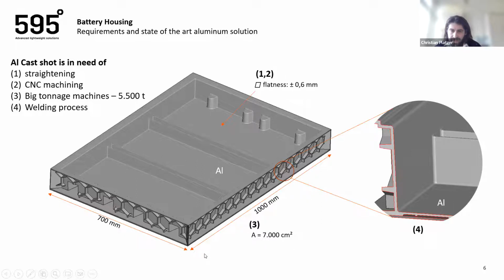And by considering this rather small dimension of a battery system, you already need a 5,500 ton machine in aluminum die casting to be able to cast it. And although there is this hype of die casting machines getting bigger and bigger, we somehow learned that there's not so many on the market, and it's very hard for the foundries to invest in those die casting machines, because the volume of the needed battery housings, for example, is not so big. So usually you cannot fill your die casting machine with only one contract. So it's hard for the tier ones to find enough suppliers.